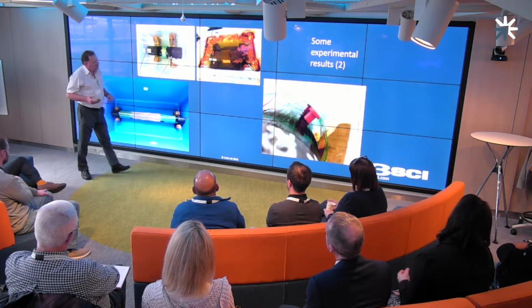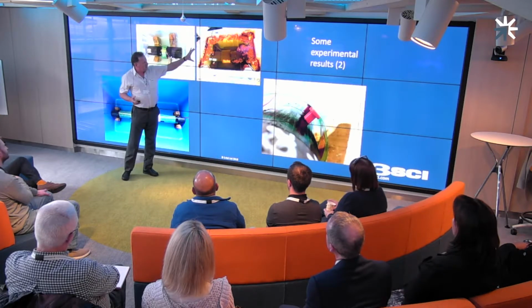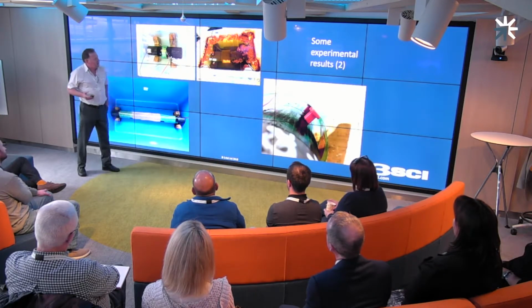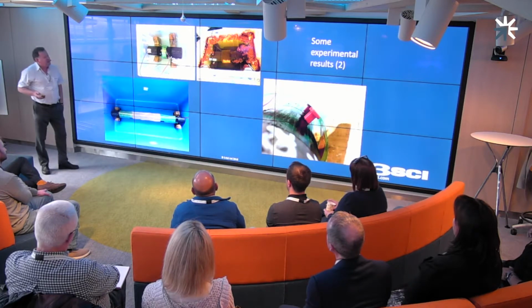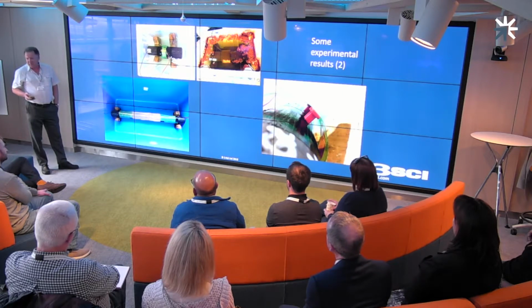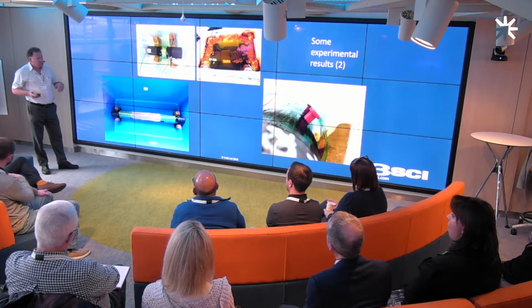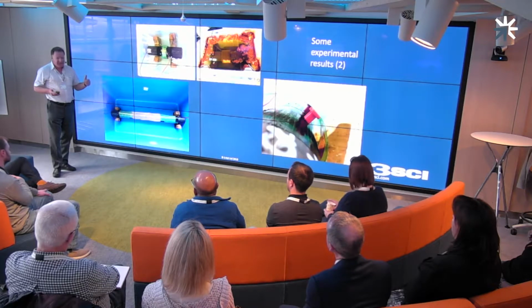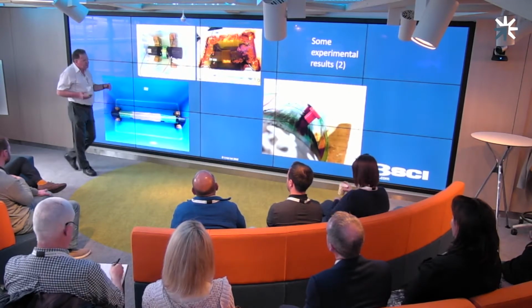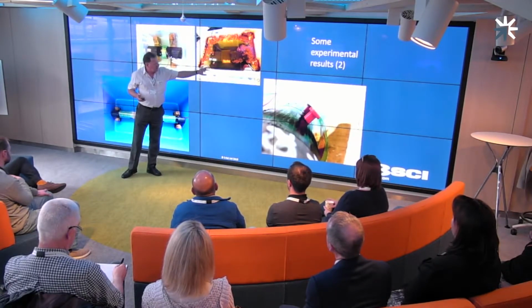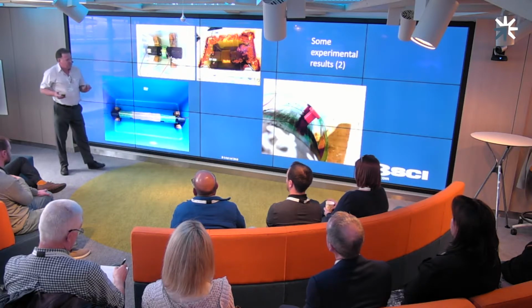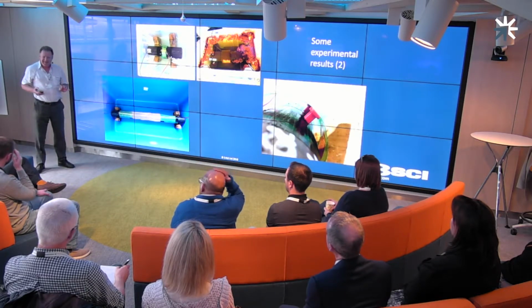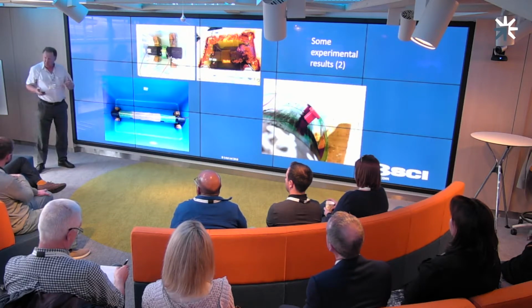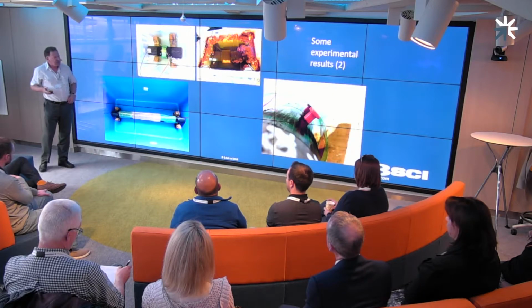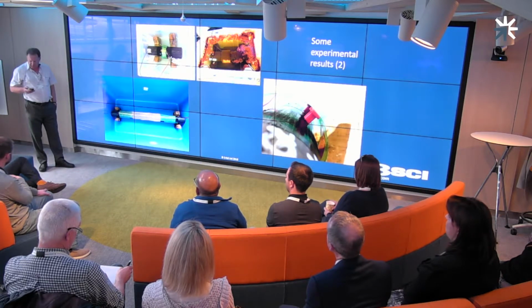And what this results in is, this is an image of the tank of that solution an hour or so after the process has been progressing. And you can see the corrosion products forming quite nicely here. You can see sort of like a reddish brown corrosion product on the surface of the liquid, which is probably a high percentage of hematite, Fe2O3. And if you look very closely, you can see the rather more darkened colours at the bottom of the tank, which does eventually turn out to be a strongly magnetic phase of Fe3O4. So it's typical rust products that transform into the sorts of rusts we find on our badly protected cars.